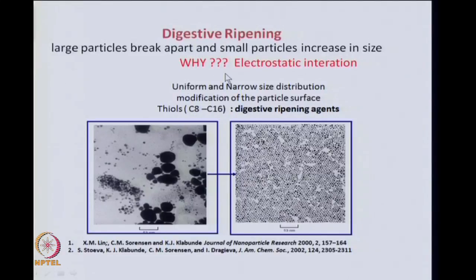And why does this happen? This is due to some external influences. For example, if you add some thiols, some long hydrocarbon chain thiols which have 8 carbons to 16 carbons. These kind of thiol molecules bring about this kind of digestive ripening through some electrostatic interactions. And these kind of molecules are called digestive ripening agents, which help in this process where instead of having large and small particles, the larger particles break to become uniform small sized particles as seen here in this particular case, which is published in these two journals.